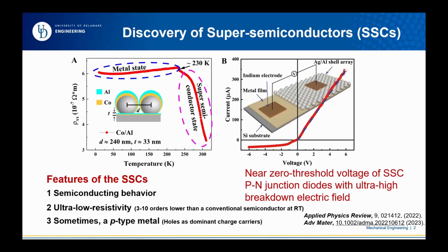So that is much higher than silicon, but comparable to high band gap materials like silicon carbide, at least on the same scale. This is right now my main focus. We try to build more devices with high energy efficiency, because you use just a very, teeny tiny amount of power to trigger the device function. So this is a new nanostructure-based super semiconductor.